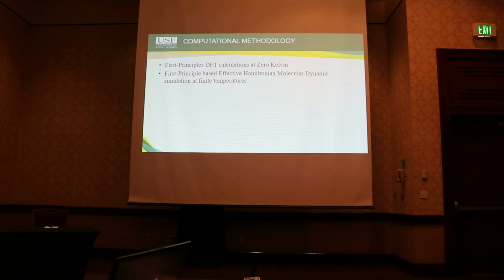So the first thing that has to be done is first-principles DFT calculations at 0 Kelvin, and then to use the insights that we gain from the 0 Kelvin simulations to then modify the effective Hamiltonian to extend it to finite temperatures.